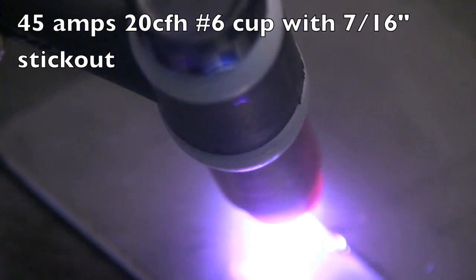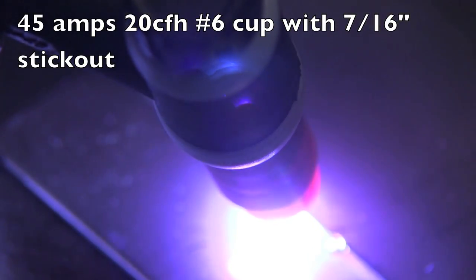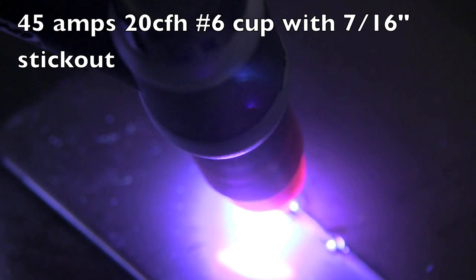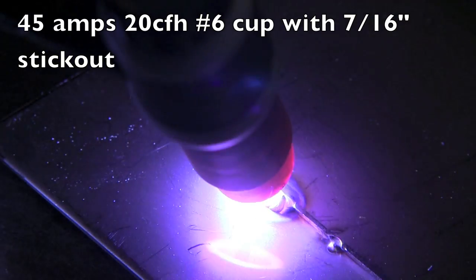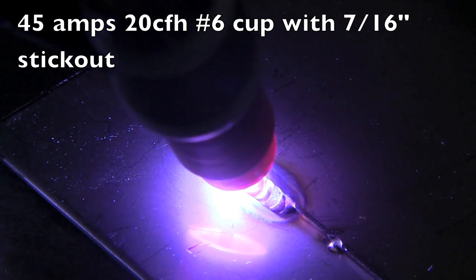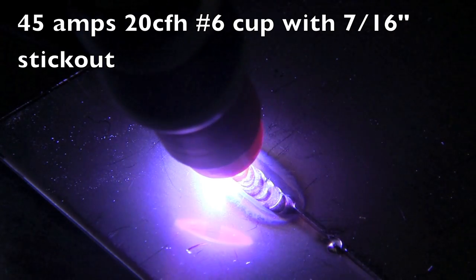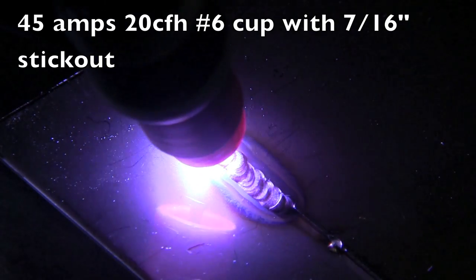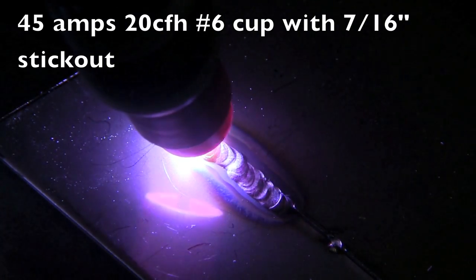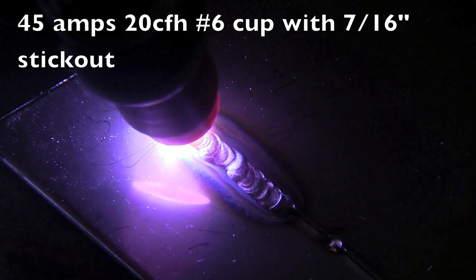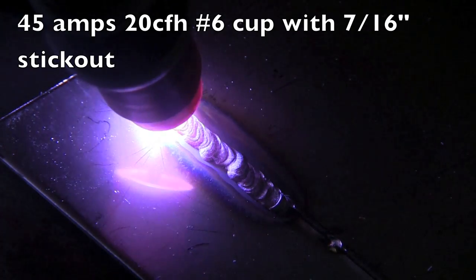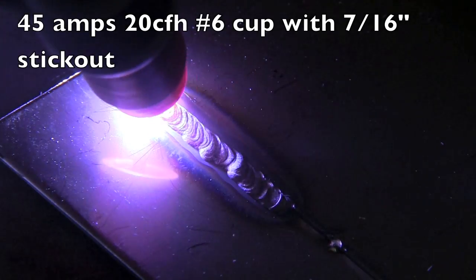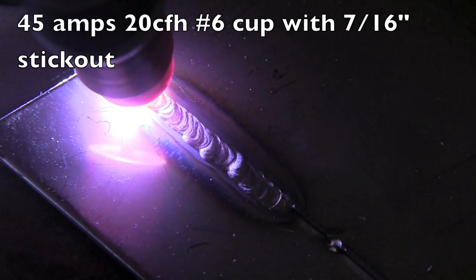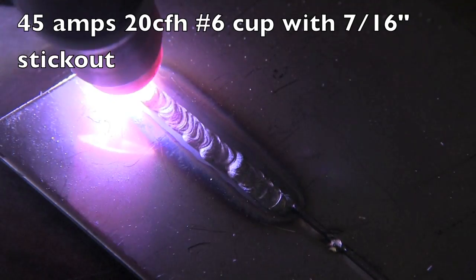I've got both of them on there. But about 7/16 of an inch using 20 CFH gas didn't really make it happen here. You can see the results here in just a minute, because even the puddle wasn't flowing right. When you don't have good gas shielding on stainless steel, it makes the puddle much more squirrely. It's sluggish. It takes a little bit more amperage to make it flow, or you have to go slower. It doesn't wet in like it's supposed to, and it just doesn't look good.